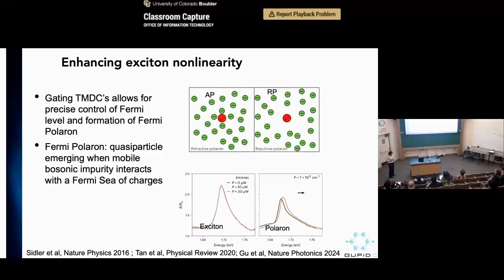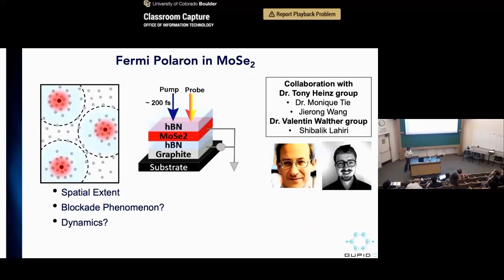So one of the things we can think about to further increase the length scale of interaction is, again, involving the charges. In this case, people have shown that you can form a quasi-particle called the Fermi polaron, where a single exciton acts as an impurity interacting with a degenerate Fermi sea. So you can have an exciton interacting with many charges and many fermions, and this Fermi sea can mediate the interaction between the excitons and enhance the interaction. People have shown that you could indeed increase the interaction, but it's unclear over what length scale you can really increase it.